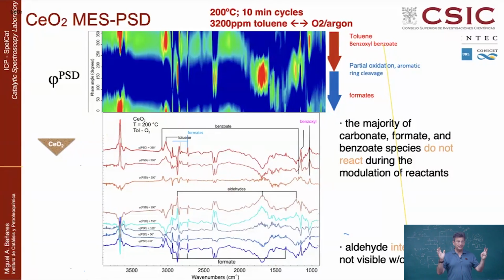Now, of all these infrared bands, many of them are gone because they didn't respond to the periodic perturbation. These are debris, residual molecules that accumulate on the surface, but they are not directly involved in the catalytic cycle. They are more like byproducts. So all these bands disappear, and all you see now are those actively responding. So the first important thing you see is what you don't see. You get rid of the spectators.